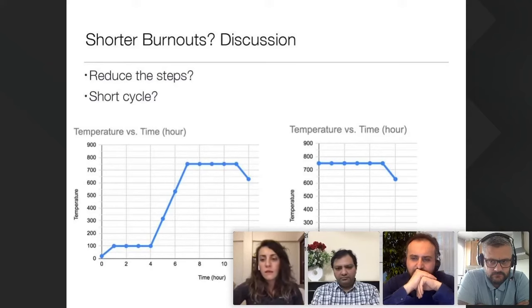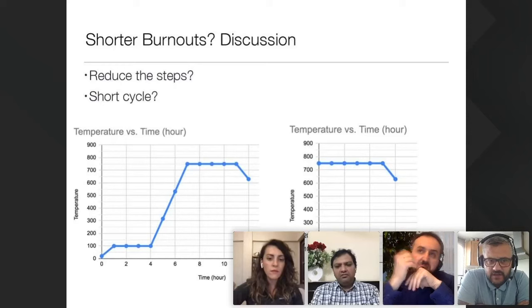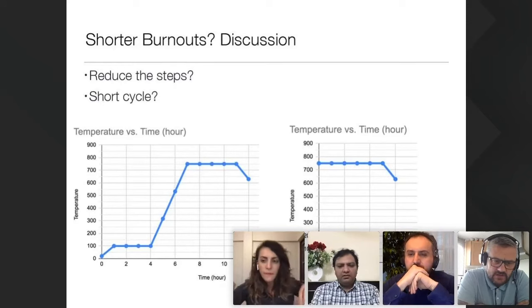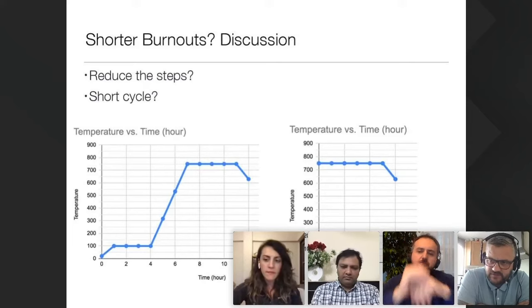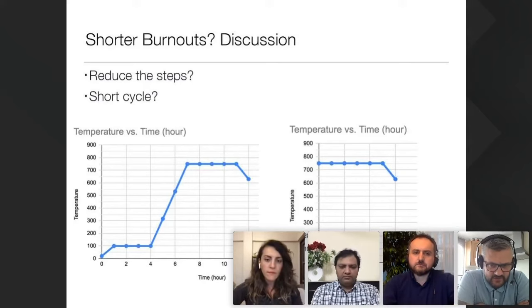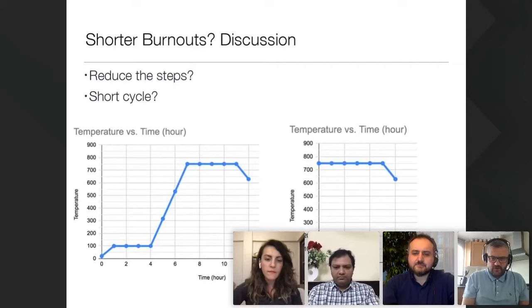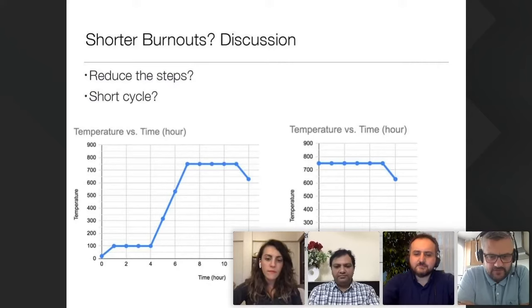Okay, great. And can we keep the investment for 3 hours inside the furnace at 30 degrees for cooling or drying? Then, with many programmers now for furnaces, you can put a delay on. So if the furnace is at room temperature, 20-30 degrees, you delay the burnout. If it's delayed for 180 minutes, it's not going to kick in for 3 hours. So yeah, perfect.